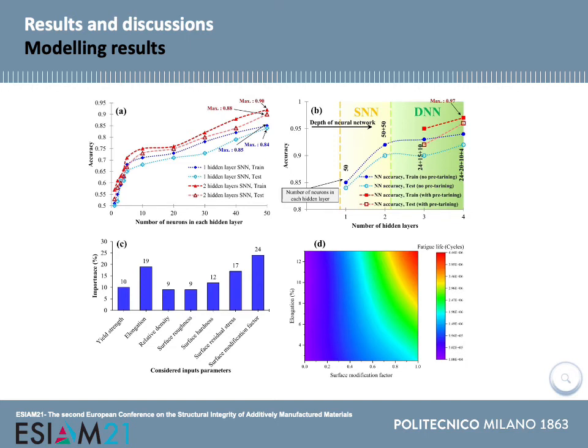After successful development of the neural network, the model function of the network was generated using the values of weights and biases for further analysis. The results of sensitivity analysis revealed that surface modification factor with 24% has the highest importance, followed by elongation. The first can be considered a parameter of the surface, and the second a parameter of the bulk material. These ranks are followed by surface residual stress, surface hardness, yield strength, and in the last rank, relative density and surface roughness both together.